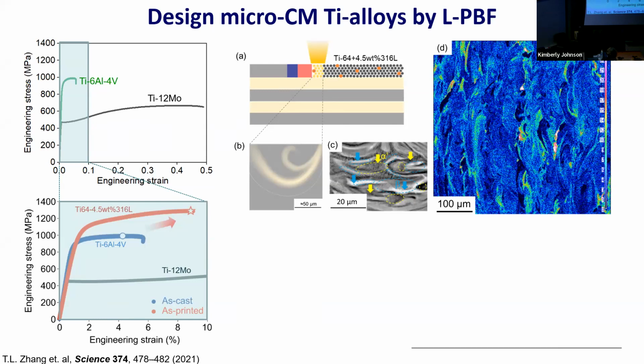The reason you have this concentration modulation is that when you form the melt pool, you can have different alloy powders with different compositions. Mechanical mixing can only mix so much. In order to fully homogenize it, you need chemical mixing, you need atomic diffusion in the liquid state. But the lifetime of the melt pool is not long enough. You don't have time to homogenize the melt pool, so you leave this concentration modulated material.